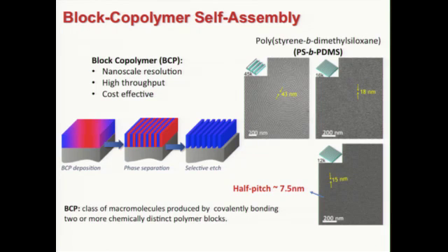Here in this work, we are using polystyrene and PDMS. Polystyrene is an organic polymer, so it can be easily etched by oxygen plasma. And PDMS is a silicon-based polymer. It's very hard, so it would survive the etching. The SEM images you see here show different PDMS lines with pitch 43 here, 18, and 15 nanometer here. The width of polymer lines is equal to the half pitch. So here we are using the 15 nanometer, so the half pitch or the polymer width is about 7.5 nanometer. And that corresponds to the channel length.